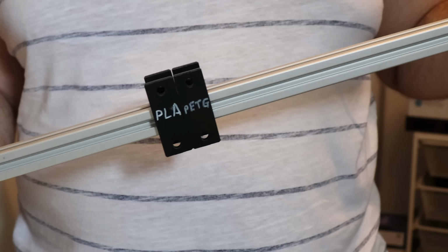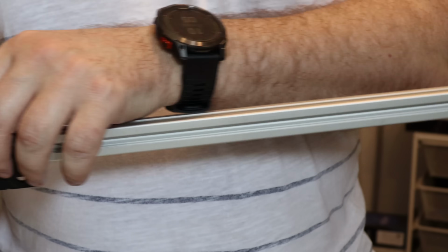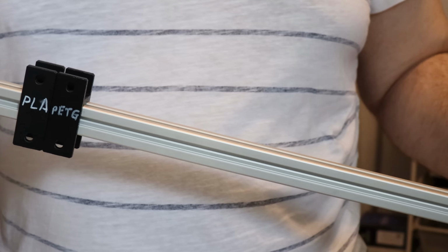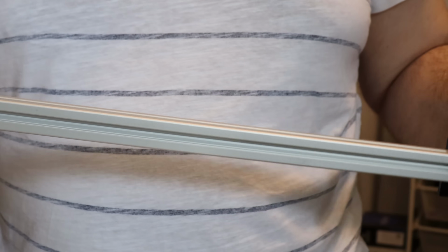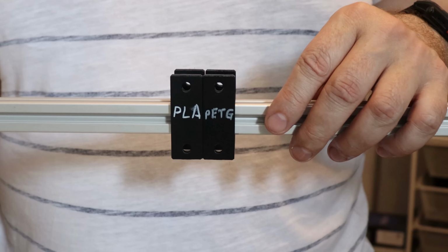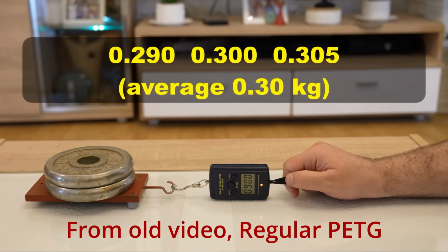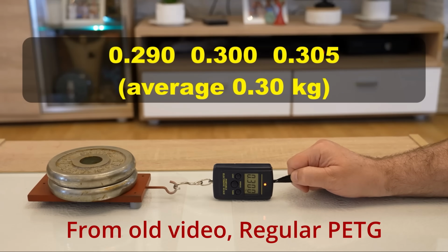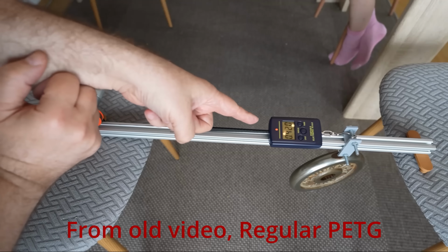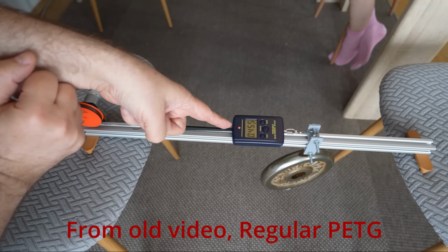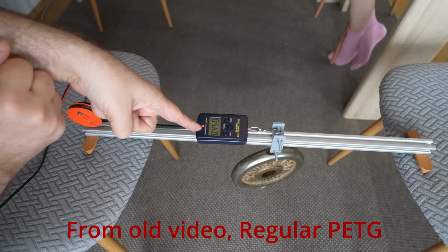Just another quick proof that PETG has a smaller friction. Here they go together, but in this direction PETG will start sliding earlier. This is from an old video. The regular PETG has a bigger static friction on the glass, but the same regular PETG has a smaller sliding friction on aluminum compared to the graphene filaments.